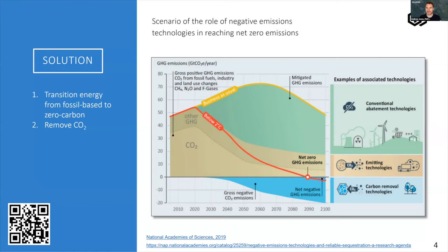we can talk then about our permanent carbon storage. So the benefit here is that this approach is incredibly low cost, but the torrefaction does something that Andrew was talking about earlier, which is we're converting the carbohydrates, which are very amenable to microbial and fungal decomposition, to something that's very difficult for them to process if it's stored in particular locations, in which case underground in this anoxic zone allows the biochar, the torrefied carbon, to be there for thousands of years. And that's a very important aspect here, as Andrew was talking about. We can verify that it's there for a long period of time just by digging it up and knowing its location. It makes it very easy to track, but it also guarantees this long-term permanence that's of interest for higher value carbon credits.